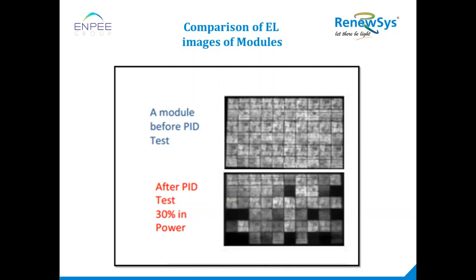The basic purpose of a solar module is not just to be protected from PID, but to generate at its maximum when installed in a field. If we increase the thickness of the EVA, the opacity is going to increase, thereby the transmittivity is going to decrease, which makes the performance of the solar module go down. So that is not a viable option, but protecting it using encapsulants like polyolefin is a better option.